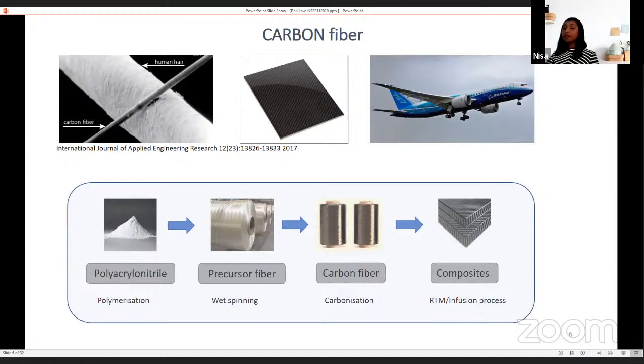So here is a quick representation of carbon fiber production. The starting material for the production of carbon fiber is a synthetic polymer called polyacrylonitrile, or PAN. Currently, about 90% of carbon fiber production is from PAN, mainly due to its good carbon yield and its stability.